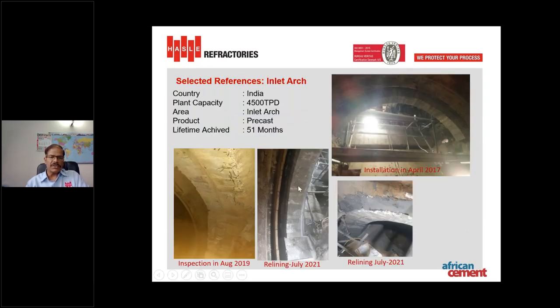Same way, we can produce and install precast for inlet arch area, where most of the plants are getting a life of only 1 year or max 2 years. But by installing these precast elements, plants can achieve 4 to 5 years life. This is a case from one of the plants in India, and the life achieved here is 51 months. Even after 51 months, the refractory was good, but as the line has to run for another 1 year, they replaced it with new lining. Same again with precast lining.